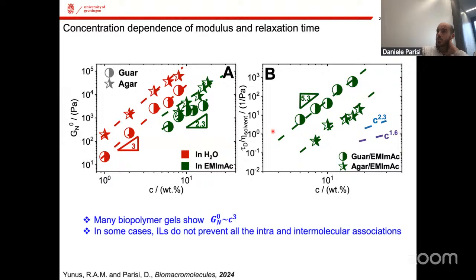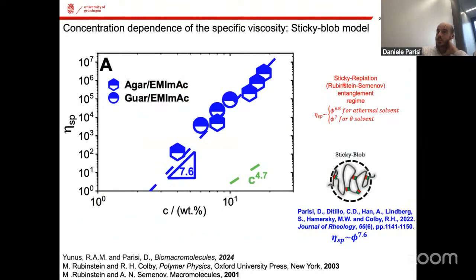So this means that if we plot the relaxation time of the material, the terminal relaxation time, or if you want, the time scale at which a typical polymer chain diffuses fully from its own network, these are basically the scaling laws we know for good solvency and theta conditions. But then you see that for our systems, we have a much stronger power law. So when we plot the viscosity and witness this very strong dependence, we are talking about associating polymers. Just as a reminder, non-associating polymers would exhibit a 4.7 slope with concentration.